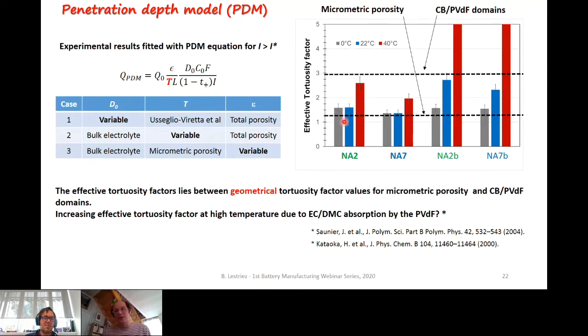But if you look more closely, you see, for example, for Na2 and Na7 at 0 and 22 degrees C, or Na2b and Na7b at 0 degrees C, that the effective tortuosity factor is very close to that of the micrometric porosity, suggesting that at these temperatures, it is the micrometric porosity that is leading the game. And you can also observe that for the electrodes containing the minimum amount of CB-PVDF, there is an increase of the tortuosity factor at 40 degrees C. And also for electrodes with the higher amount of CB-PVDF, you have a very significant increase of the tortuosity factor with the temperature.